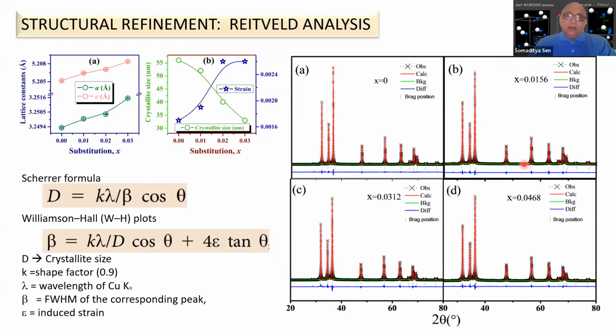Okay. Now, what the refinement looks like. The black points, the cross ones, are the experimental data, and you can see we have fitted the experimental data with our refinement, and we can find that it has fitted very well. The residue, the difference between the theory and the experiment, is given by this blue line.